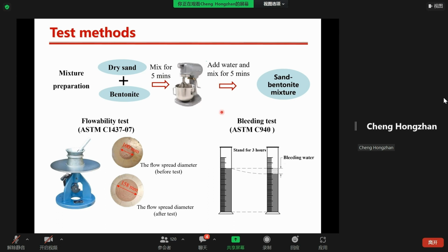This process is similar to the first phase of the cut-off wall construction. Then the workability of the fresh sand bentonite mixture was immediately tested with the flowability test and the bleeding test. The flowability test used the flow table method, with a standard flow mold and flow spread diameter measurement. Apparently, a large flow spread diameter means a higher flowability.